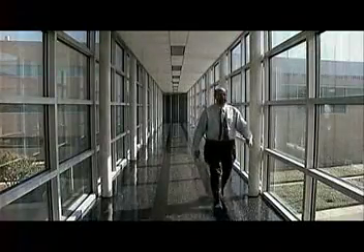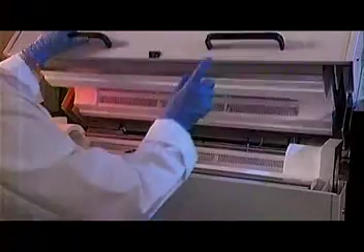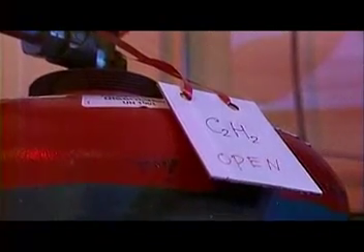Deep in the heart of Texas, scientists are taking a different approach to assembling carbon nanotubes. It's the dream of the future, but it's an achievable dream. To make a batch of carbon nanotubes, bake a silicon plate coated with iron particles at 1,300 degrees Fahrenheit in a special oven. Then add a dash of acetylene, a gas that contains carbon. When acetylene comes in contact with the iron, it releases its carbon atoms, which assemble, as seen here, into nanotubes.